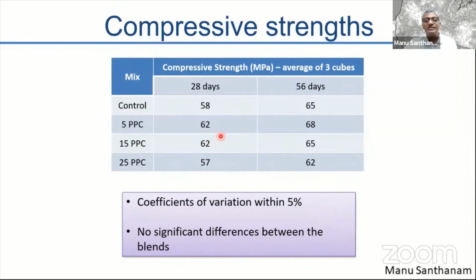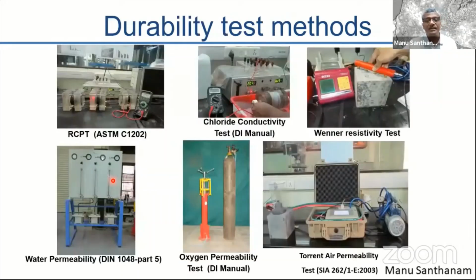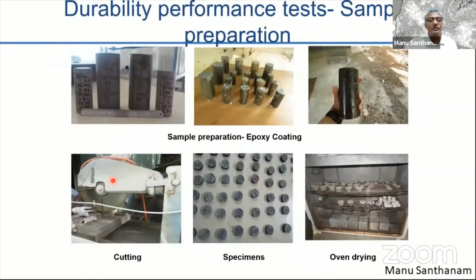The compressive strengths, of course, you can see are not much different irrespective of the degree of replacement of the bagasse ash. So more or less you have consistent performance. We did several different durability tests, chloride related, water related, and gas related. And you can see some specimens that I prepared. Somebody had talked previously about the color of the concrete. So here you can look at the color of concrete with bagasse ash. It's looking very dark.